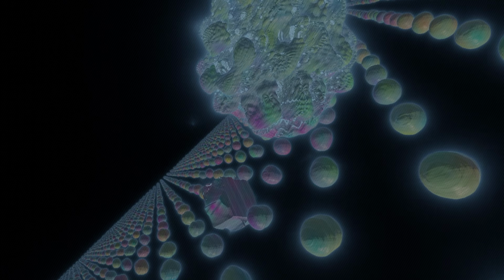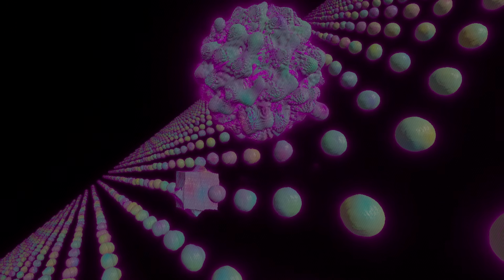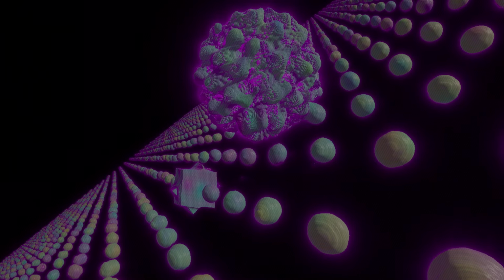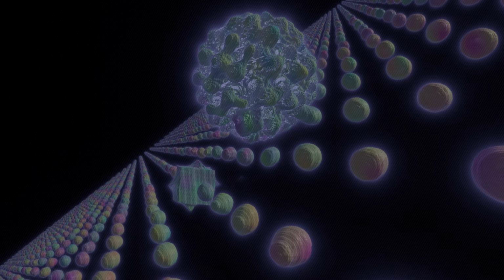Exactly. And that flip, represented by adding or subtracting G, signifies a major change in the direction of momentum flow. It effectively degrades the total momentum flux carrying the heat. Umklapp processes are the dominant mechanism for intrinsic thermal resistance in crystals. They're the main reason heat flow isn't infinite. They become important mainly at higher temperatures, maybe above one-third of the Debye temperature, when you have enough high-energy, large-k phonons populated near the zone boundaries to make these G-vector processes likely. And importantly, umklapp scattering is a direct consequence of the discrete, periodic nature of the crystal lattice. It wouldn't happen in a continuous medium.